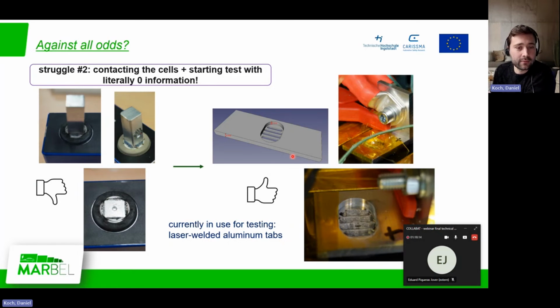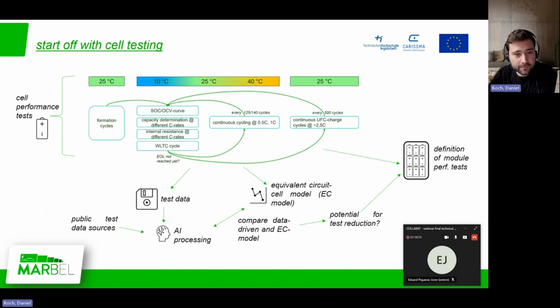So therefore, we were thinking about a mechanically more stable, more sophisticated setup, which is also the one currently in use. We had slotted holes in a milled aluminum plate and just laser welded those to the tabs. Another important advantage of this solution was that we had a higher current carrying surface compared to the 4 laser welded seams of the rectangular solution. So this is the current solution we have: laser welded L-shaped tabs to attach the test bench cables, and also used in the setup for the cooling rails, which I'll show in a minute.